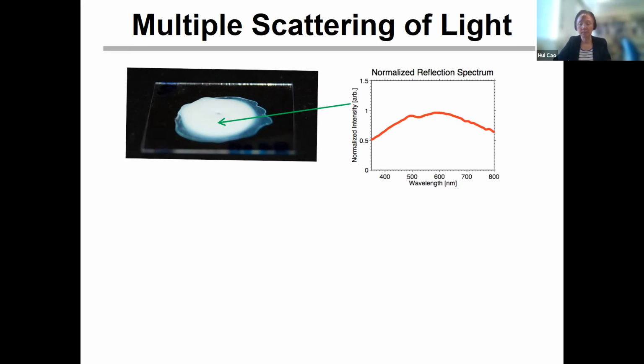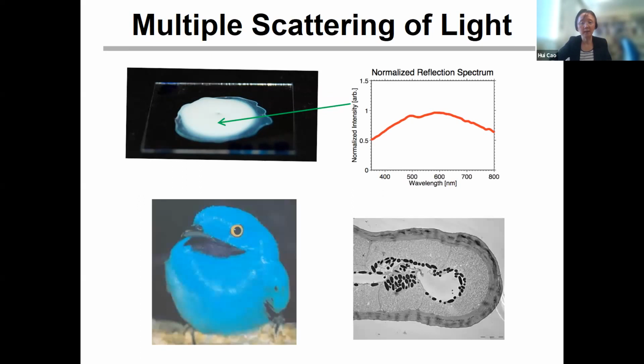So then we say, how did birds do it? Okay, so now we go back to see again, this is a bird feather. Here is a low magnification cross section of a feather barb. Outside is the skin, and then the color producing structure is right underneath the skin. You can see that they are not very thick. It's about 10 microns. And then after that we see this melanin, which is a black pigment absorbing all colors.